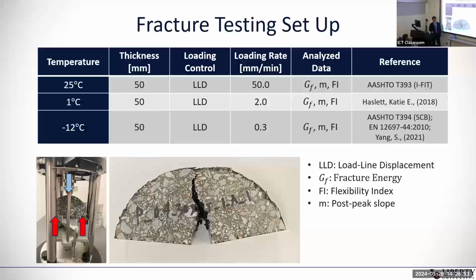For minus 12 degrees C, there is AASHTO T 394, which is the standard SCB fracture test at the low temperature. And that's why we picked minus 12, since we use the PG 64-22, and then 10 degrees above the lowest temperature is the one that we use. But this standard uses 25 millimeter of thickness in the specimen, but to be consistent, we use the 50 millimeter thickness of the specimen.